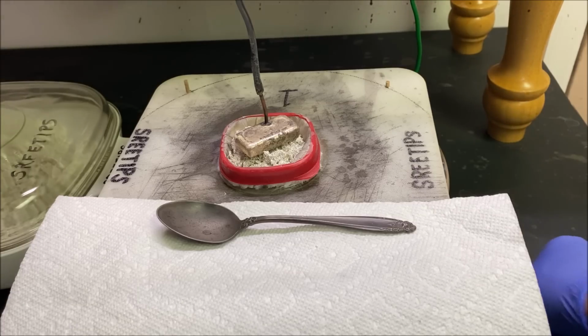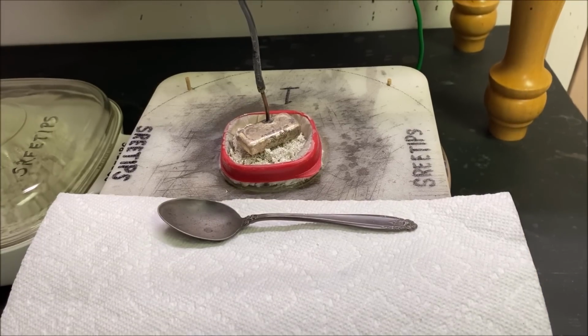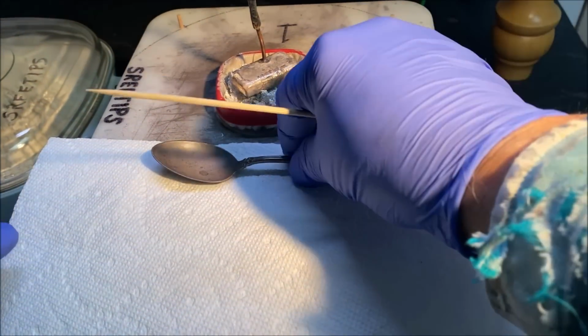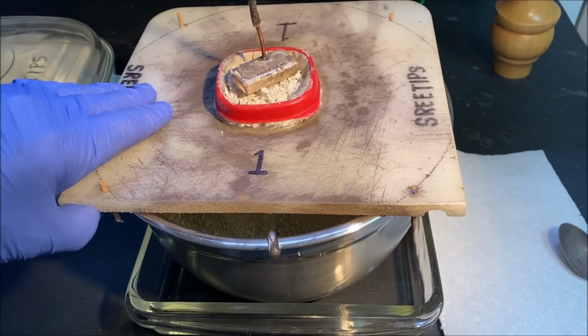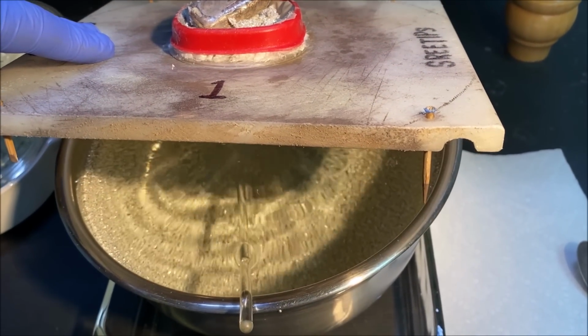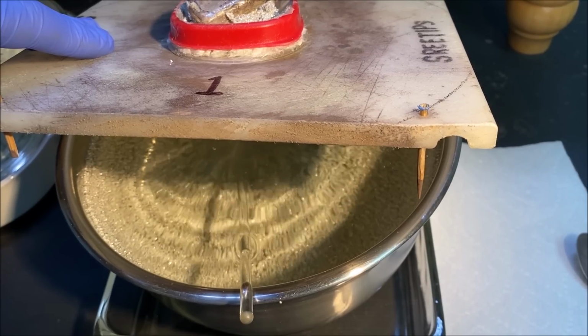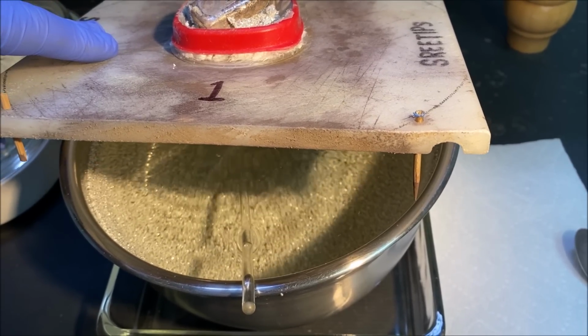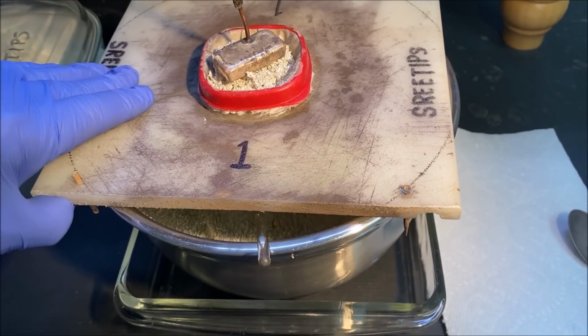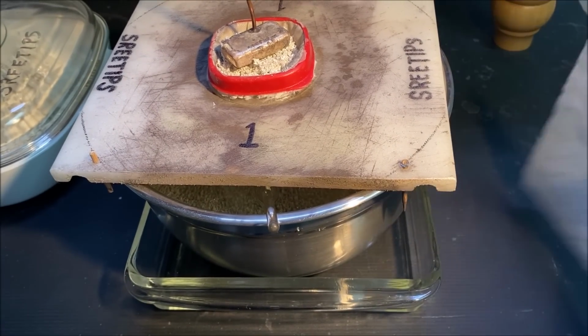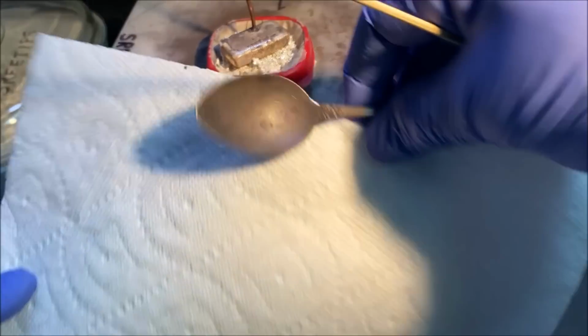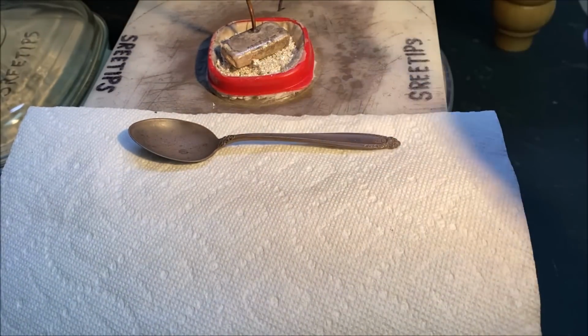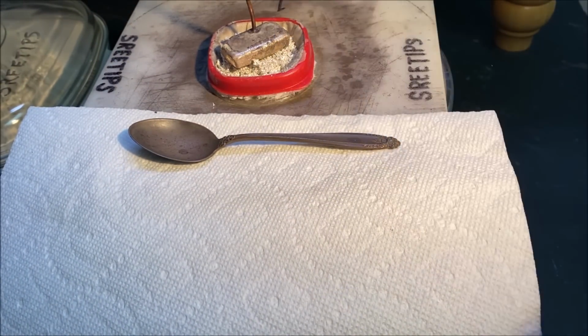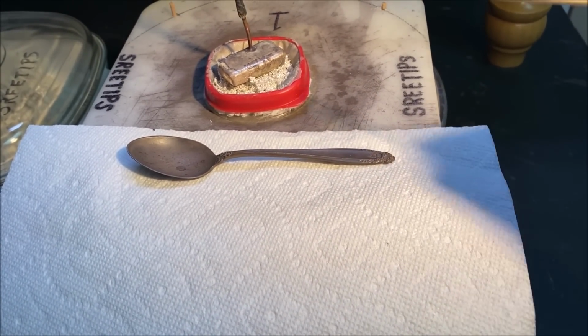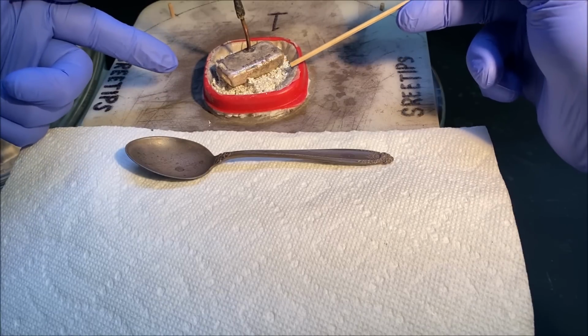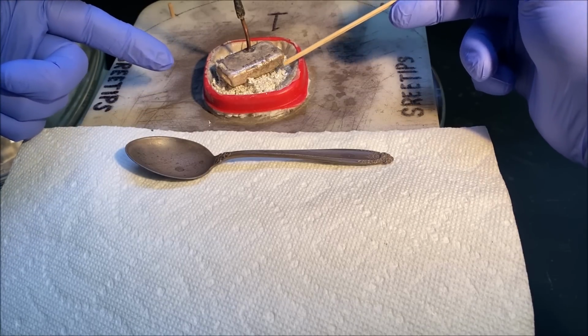This is about 23 hours into the operation of the silver cell, and if you look down in here, we've got some nice crystal growth going on. The solution is staying clear and colorless, as it should. And what little impurities are in this silver that we're feeding in will end up getting trapped in the anode filter here.